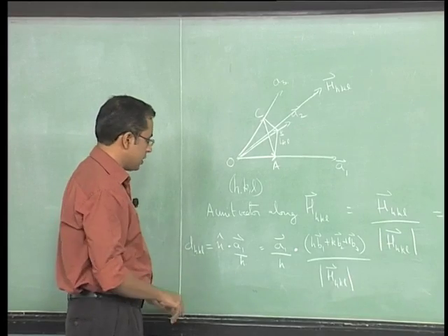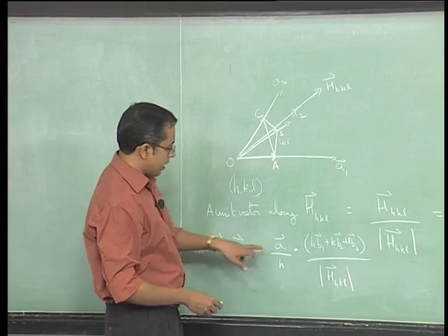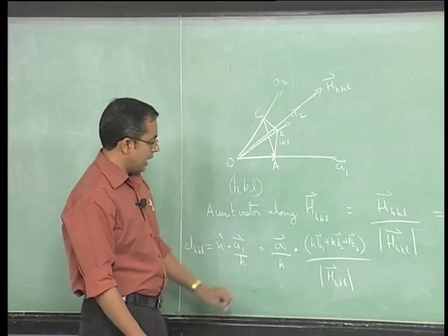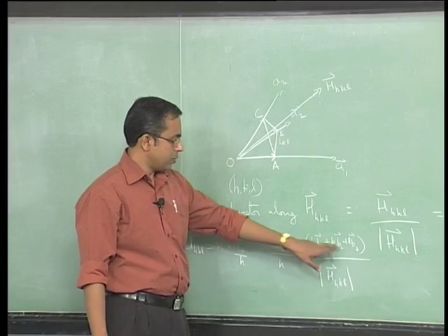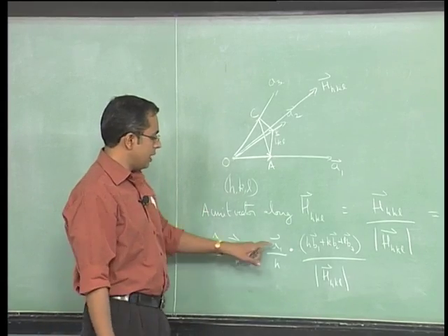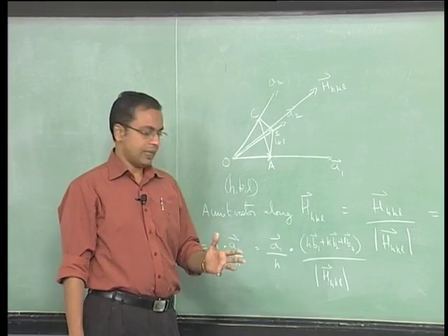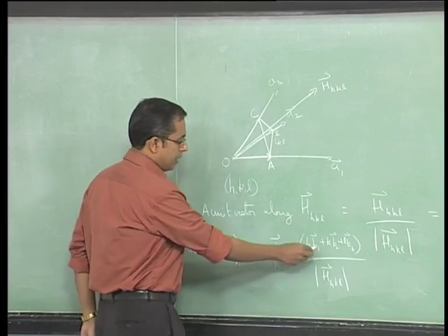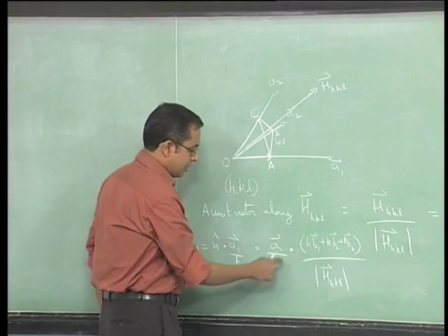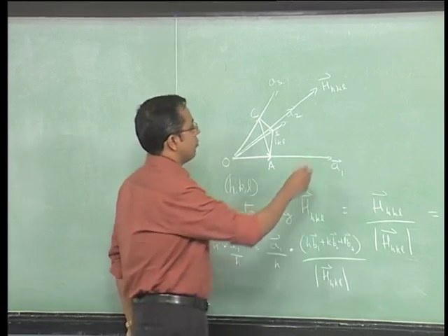So now if we carry out this dot product, what do we see? Again you have A1 here, you have B1, B2 and B3 here, and clearly A1 dot B2 is 0 and A1 dot B3 is 0, the way we have already seen. So only A1 dot B1 is going to count for anything else. A1 dot B1 is going to be 1 because of the way it is defined, and the H and H are going to cancel. Therefore